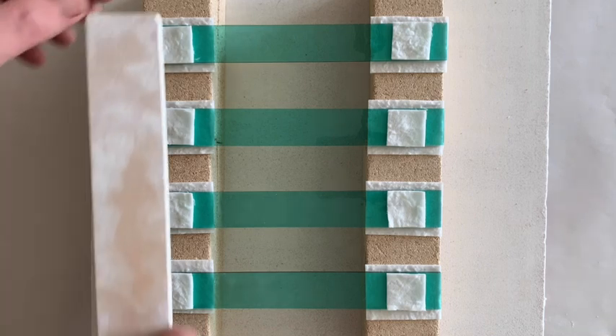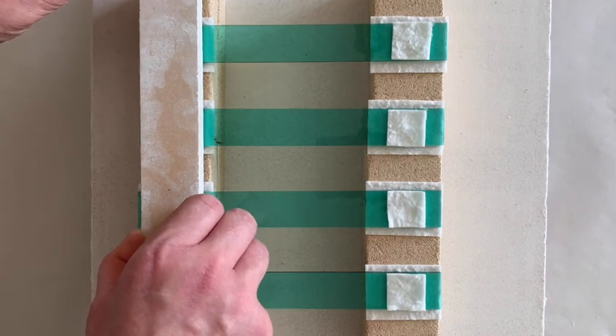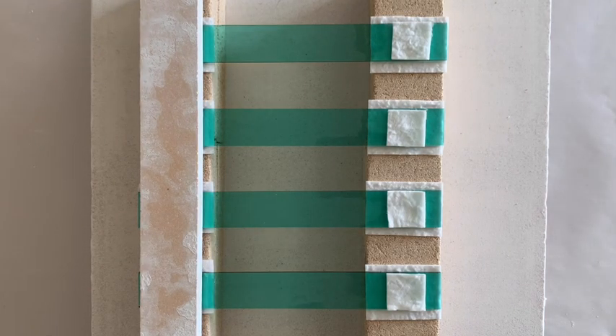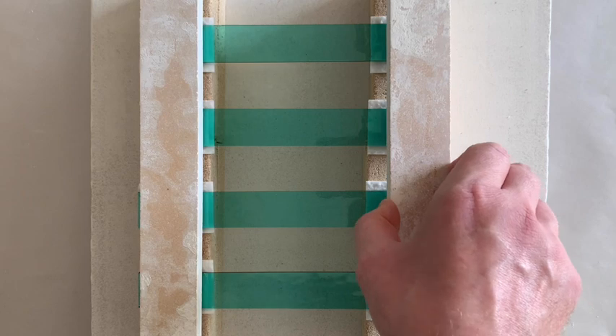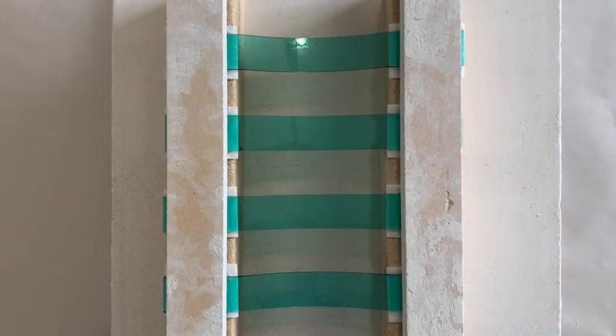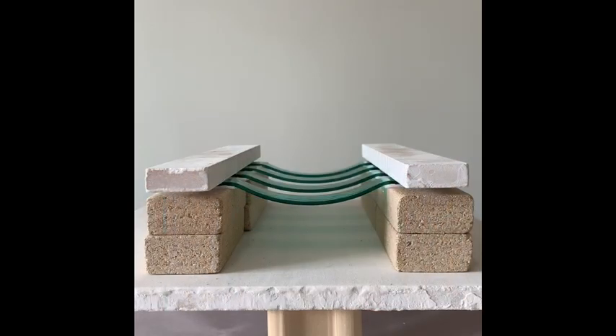Finally, lay a second set of dams on top of the fiber paper to hold the glass strips in place. Fire the glass strips at 300 degrees Fahrenheit per hour to 1150 degrees Fahrenheit and hold for 10 minutes. If you have even heating in your kiln, all the strips will have slumped to the same depth. If the strips slump to different depths, you may have a hot or cold spot in your kiln.